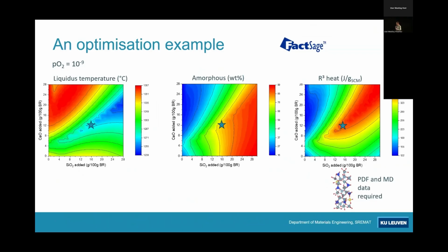So we calculated here 3 different items. Liquidus temperature, the lower the better, because we know at the Portland cement kiln we can go up to 1450 degrees Celsius. The lower we are, the better. We want to stay at a maximum of around 1300 degrees liquidus temperature. Amorphous content, which we could calculate using the glass forming ability. There we want to be around 70 to 80%.